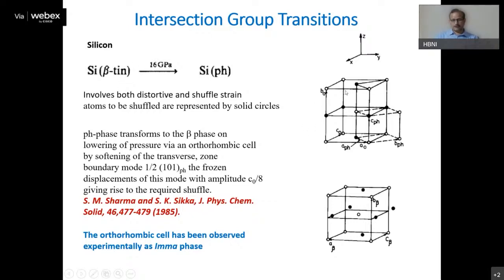So atomistically, you can consider it like this. This is the unit cell of your beta-tin phase, and if you take these atoms and introduce some shuffle movement to these solid black atoms like this, you can get the primitive hexagonal phase. So in this case, again, there should be an intermediate phase, which would be a subgroup of the groups describing the symmetry of the initial and daughter phases. And there should be some phonon mode which will soften to describe this phase transition.